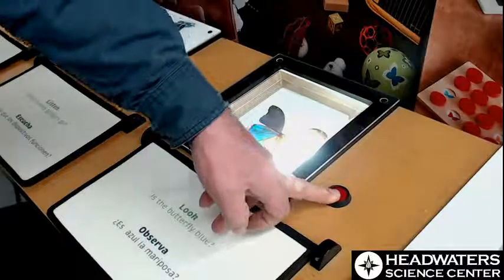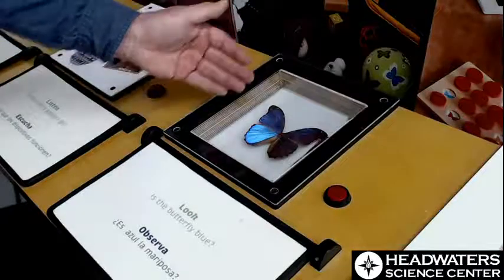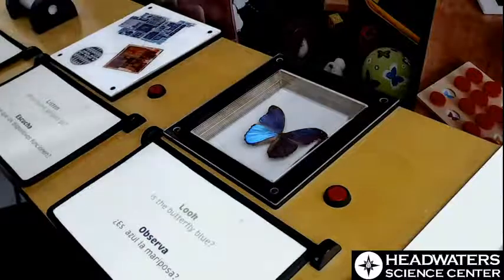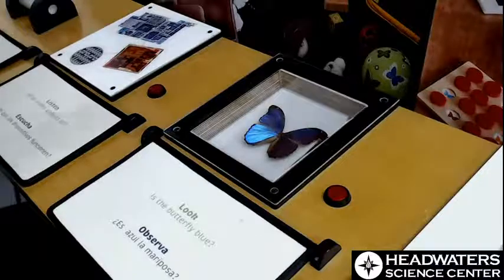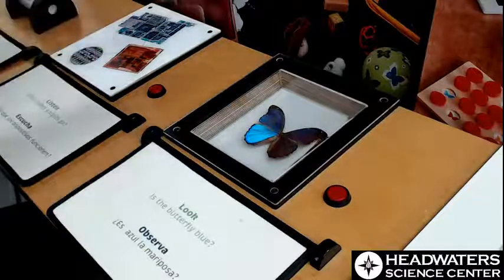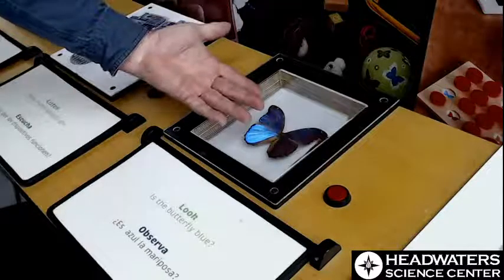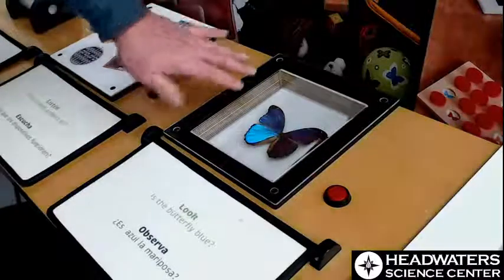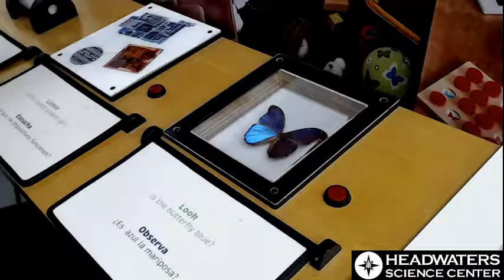And the reason that it looks blue is because if we could get it to a larger scale, or to a bigger impression and scale up, we could see that there are channels in there. They're actually 200 nanometers wide. And what they do is you get light reflecting in those 200 nanometer channels. And so it's built with ridges and channels. And the reflective image from that to our eye is around 400 nanometers. It doubles actually coming back out of that. So what we see is this brilliant blue, which is in that 400 plus nanometer range.